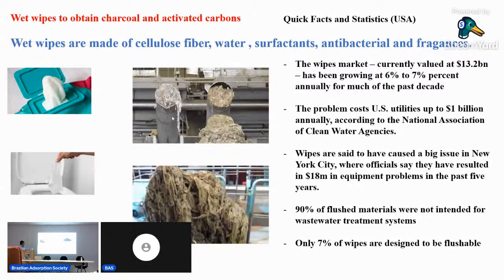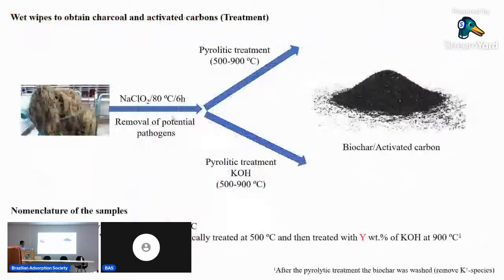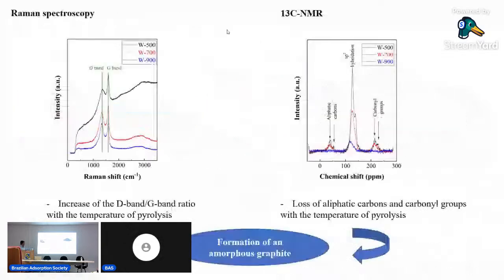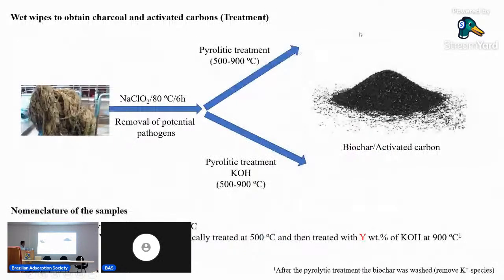First, we need to remove the potential pathogen by bleaching. It's a low-cost treatment. And later, by pyrolytic treatment at different temperatures, or by pyrolytic treatment but with a potassium treatment, we have a biochar, activated carbon. So we can identify by Raman spectroscopy the D and G band ratio with the temperature of pyrolysis, but also by solid-state nuclear magnetic resonance, we can demonstrate the loss of aliphatic carbons and carbonyl groups with the temperature of the pyrolysis. That is where we have the formation of amorphous graphite.